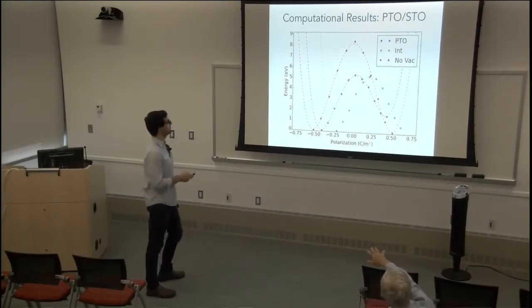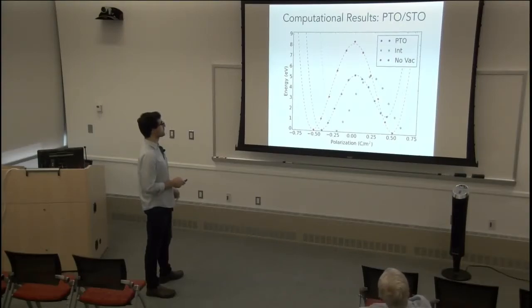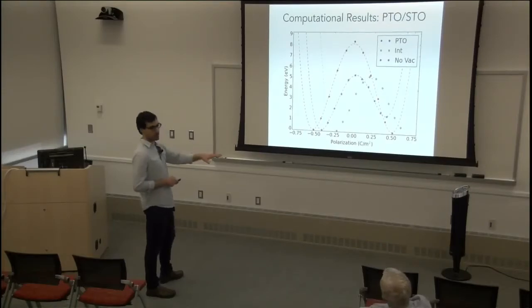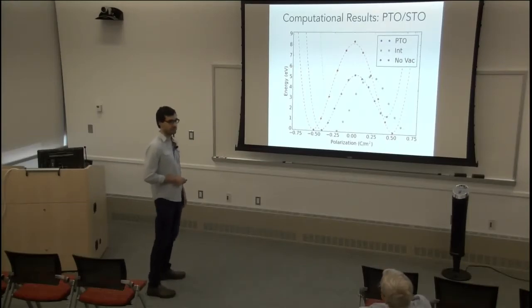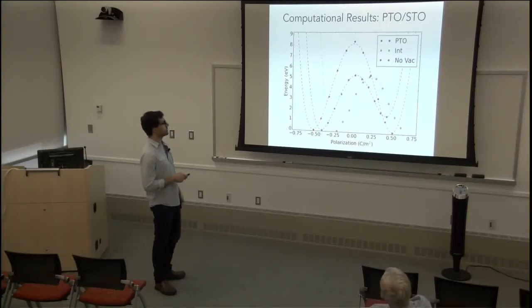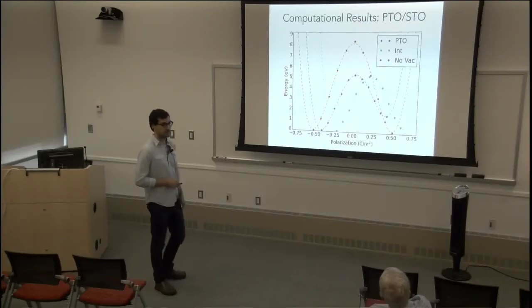So what you do is you start with some negative state and some positive state, and you let the system relax. So you calculate, and then you have two points, these two ground states. Then you linearly interpolate the atomic positions and do a one-shot calculation, and that's how you get these points in between. Then calculate the polarization. Do one step, don't do any relaxation. You're only relaxing these two points.